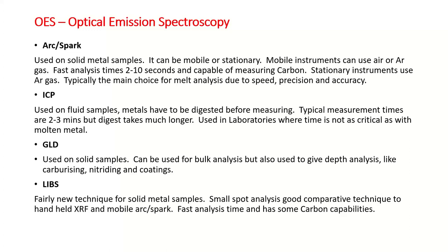It's also good for coatings, so if you've got some coatings on there, you'll be able to work your way through it. And LIBS, as I say, is quite a new technique. It's quite a small spot on there, and it's a comparative technique to the handheld X-rays and the mobile spark instruments. It's quite fast, and it has got some carbon capabilities, although at the moment, if you're looking for L grades on stainless steels, then you're going to be pushing the technique a little bit, and everything has to be almost perfect to be able to get a good result out of them. But as we say, it's quite a new technique. Technologies are changing very, very quickly, and I don't think it'll be too long before that's going to be one of the techniques to go to.